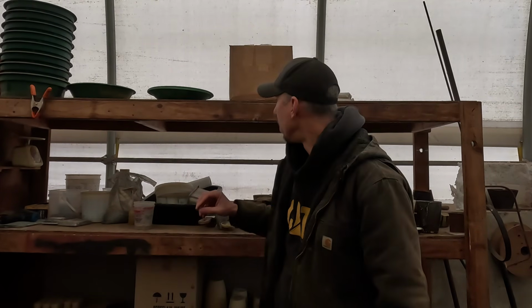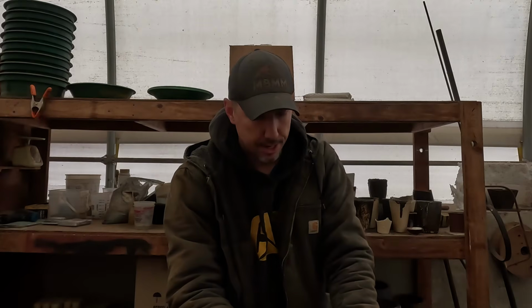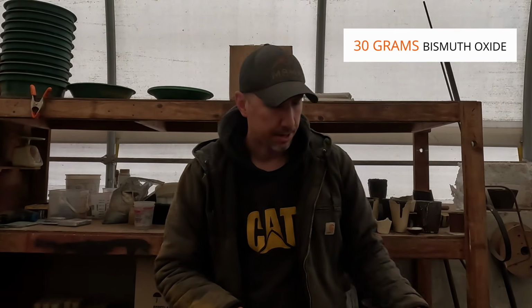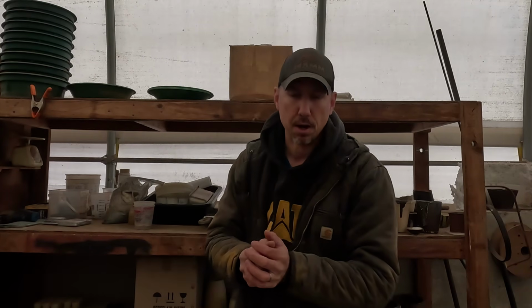Now we got to add kind of the seasonings, if you will, right? We're going to add some bismuth oxide here. Bismuth oxide is going to act as our collector metal. I don't know if this is 10% gold or silver, or if there's just a few little minor particles of gold and silver. And bismuth oxide is going to act as a collector. So we're going to add enough metal to the system where the bismuth can come down like rain through that flux, that slag that's melting, and collect all the little particles of gold and silver and bring them down to the bottom of that crucible.